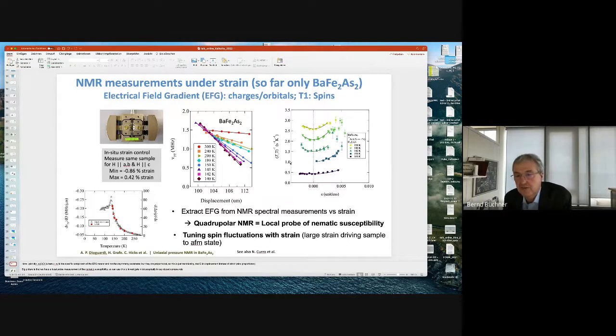This is a relaxation rate as a function of this strain, and you see for some of the samples it increases, you see a peak, and it goes down at some temperatures. So you really induce now the magnetic order via this strain, and this is of course coming via this coupling, which is not a big surprise in these 122 systems where these phase transitions are strongly linked. And we are now trying to do the same experiments also for other systems and looking for better understanding what is really the role of these magnetic fluctuations if we have these unusual nematic fluctuations.